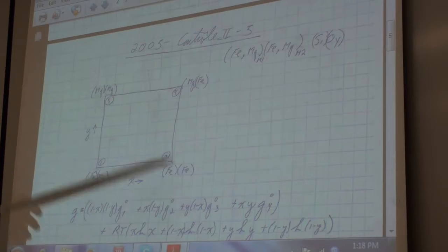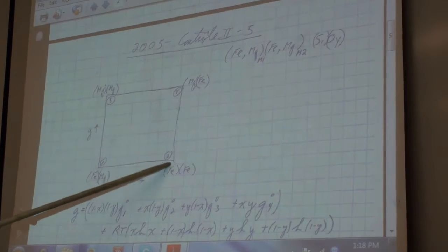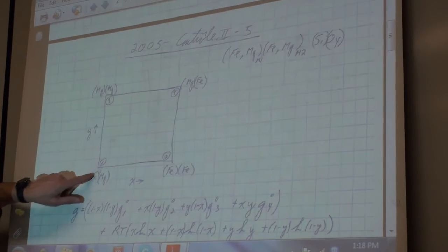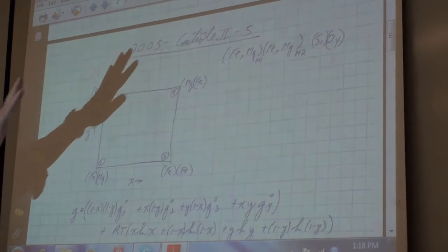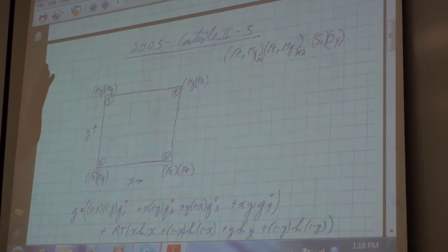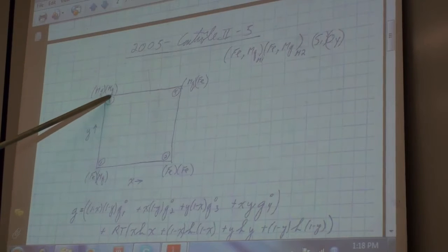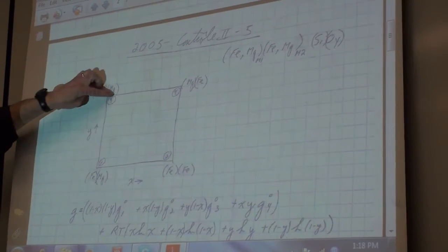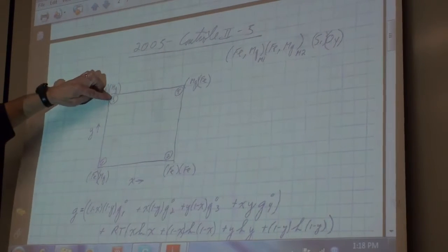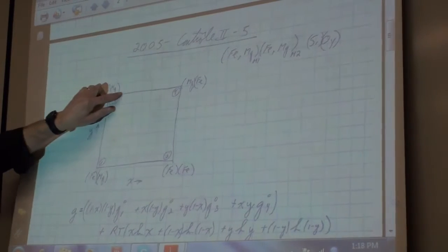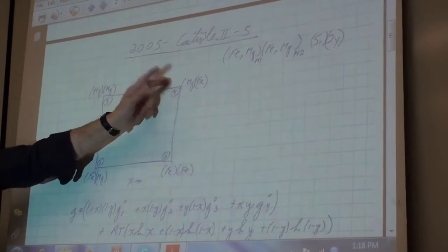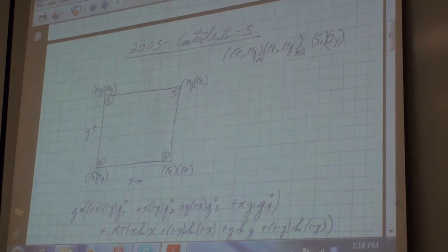Your real composition path would be the diagonal here, where the number of these and the number of these was equal. The magnesium and the iron simply distribute themselves randomly. But in actual fact, you're either going to curve around this way, or you're going to curve around the other way, depending on which sites are preferred. And that's basically what this model parameter is going to tell you.